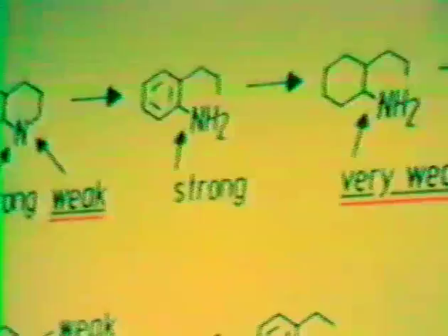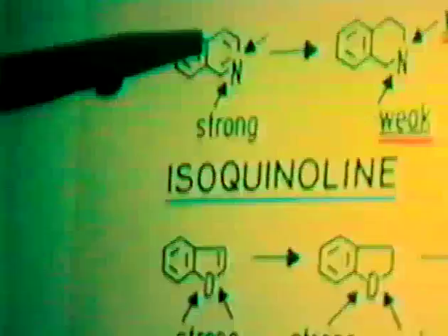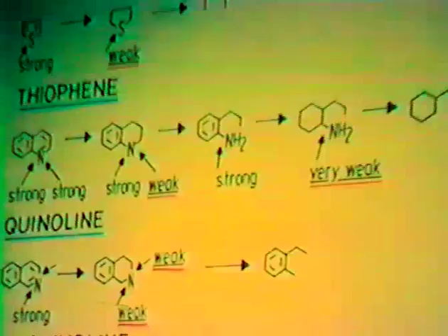So the weak bonds. For instance, it's a nice question what HDN activity means. If we look at the conversion of quinoline, the nitrogen is nicely shielded in this aromatic ring, and only after hydrogenation does this bond become weak. This one becomes weak, but this one is still strong, and so this one is split in the later step. And now, after hydrogenation of this ring as a slow reaction, this one becomes weak and it's easily split, and we end up mainly with the olefin as a precursor of the saturated compound.